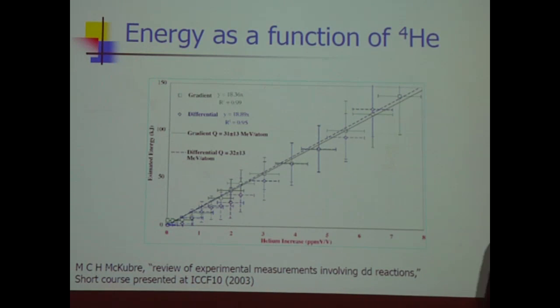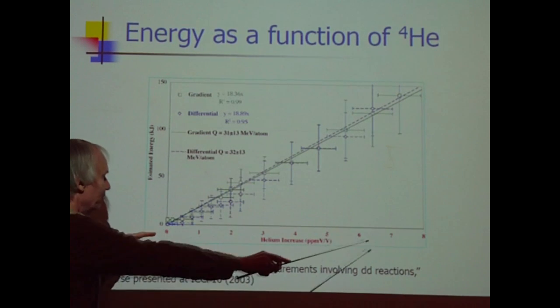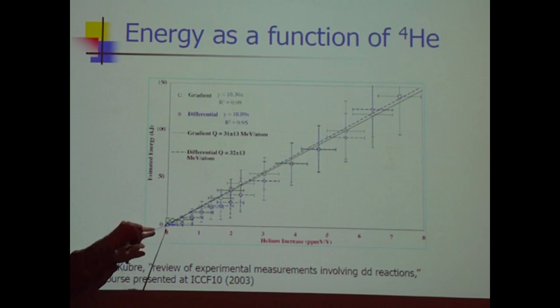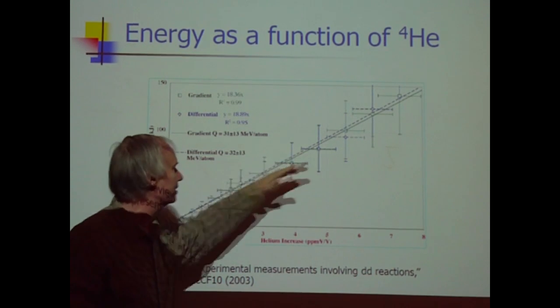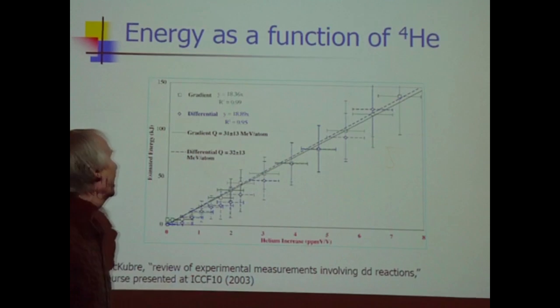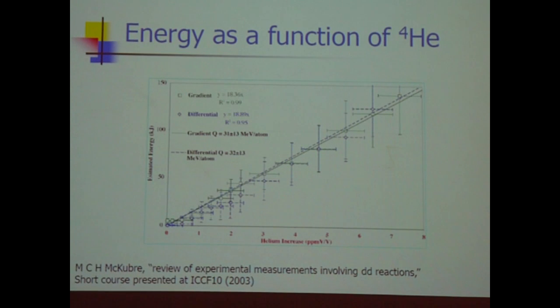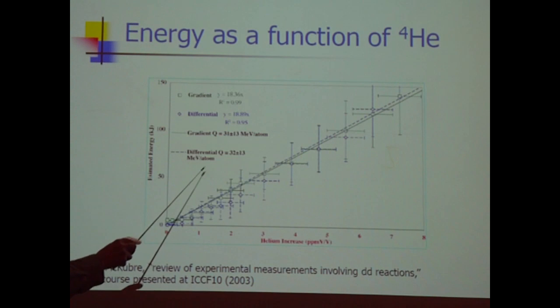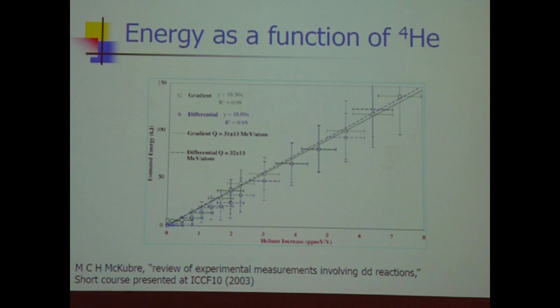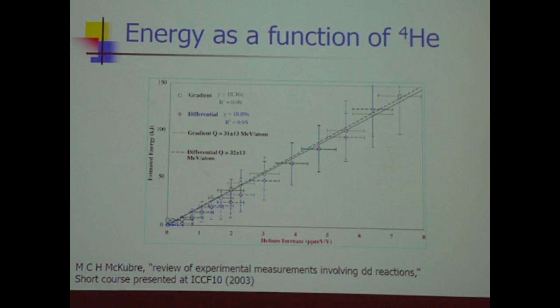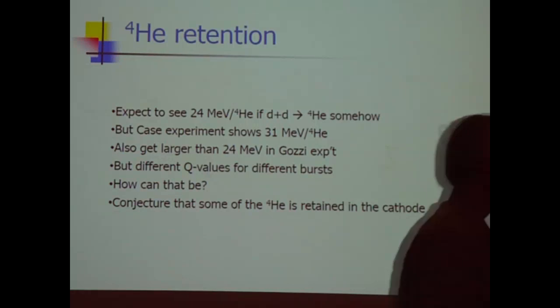So from that, you can plot helium increase correlated with the energy produced. So you get experimental data points, and you can draw some lines through it. And the lines through it, the hope is 24 MeV per helium-4. What we see is 31 or 32 MeV per reaction. So we're not getting 24 MeV. We're getting a higher number. Scratch your head and you say, well, that's discouraging. What reaction happens at 30 MeV? Well, of course, there isn't any DD to helium-4 reaction that occurs at 30 MeV.